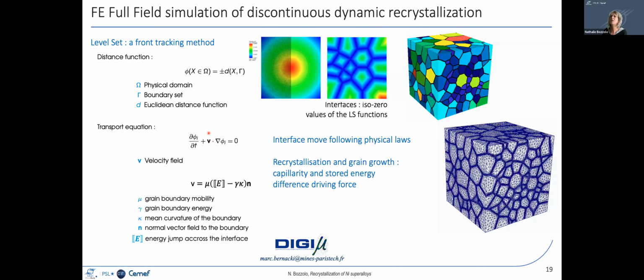implemented, because this velocity field describes actually the mobility of the boundary, of the interface, and the driving force acting on it. So here we find again the differences in stored energy and the capillarity forces we have described before. So we have exactly the same physical laws in these models as what we were using before in the mean field model.